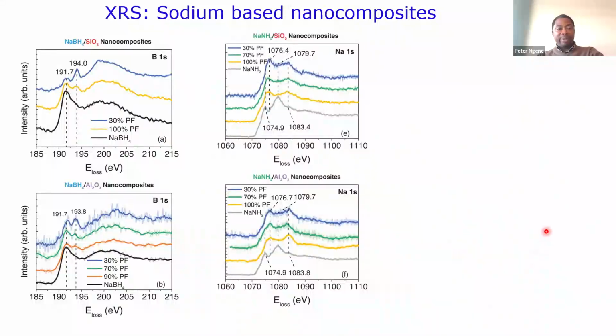We also did the same thing for sodium borohydride, the sodium-based material. We saw a similar thing. We do see the appearance of this peak around 194 eV, which signifies the tetrahedral boron. And we conclude that the type of scaffold matters, silica has a different effect from alumina. If you look at this carefully, we see even where these peaks appear is different. Here we have 194. In this case, we have 193.8. So slightly different for the alumina-based and the silica-based nanocomposite.